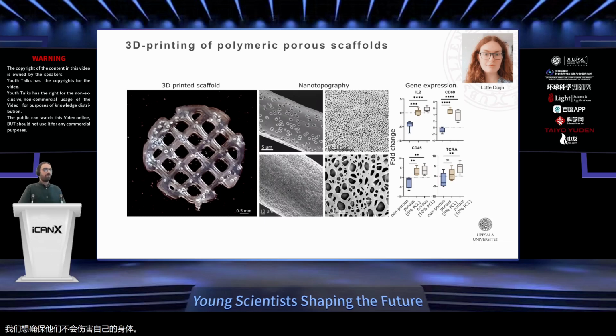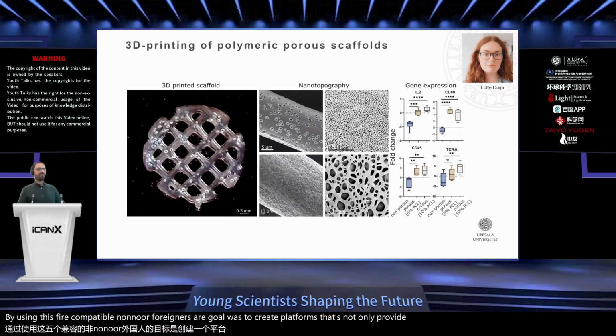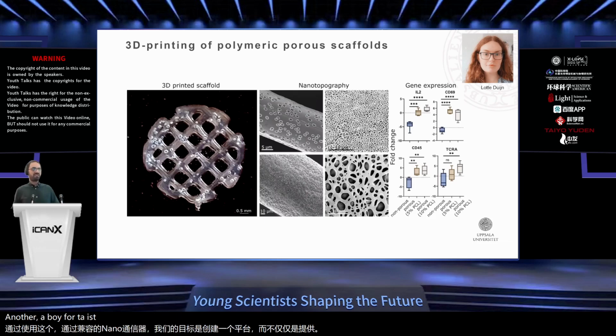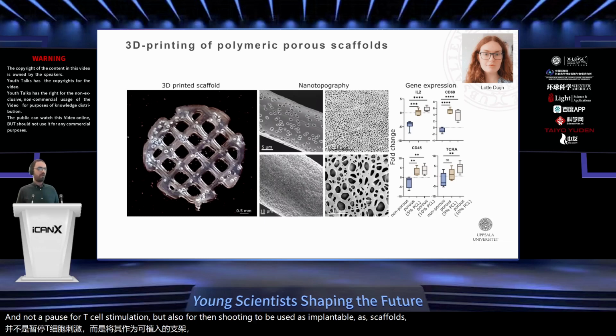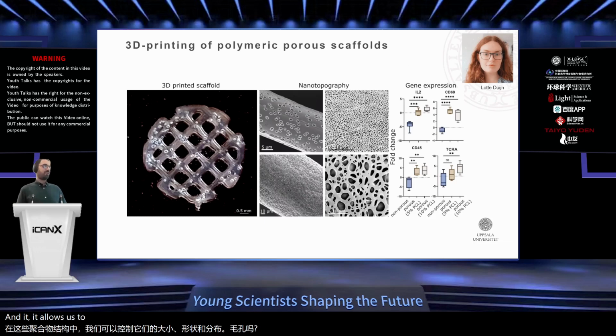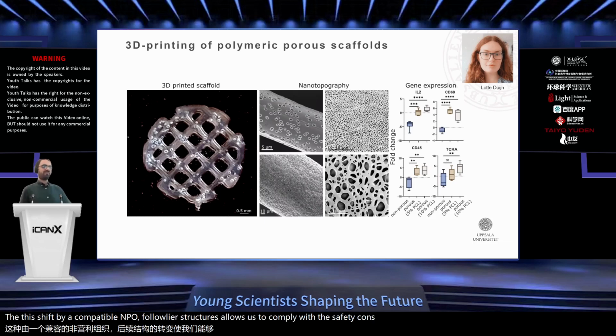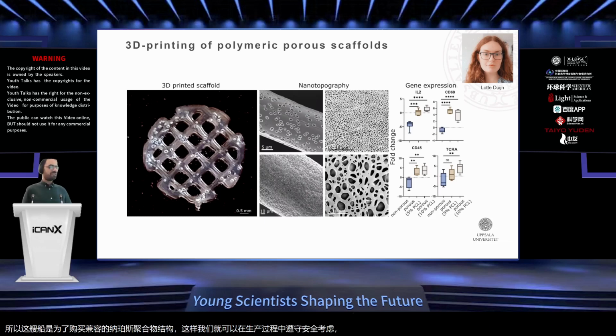By using these biocompatible nanoporous polymers, our goal was to create platforms that not only provide the nanopores for T cell stimulation, but also potentially can be used as implantable scaffolds. In these polymer structures, we have control over size, shape, and distribution of the pores, and it allows us to optimize how T cells interact with them. This shift to biocompatible nanoporous polymer structures allows us to comply with the safety concerns during the in vitro production of CAR T cells, which is important for potential applications in immunotherapy.